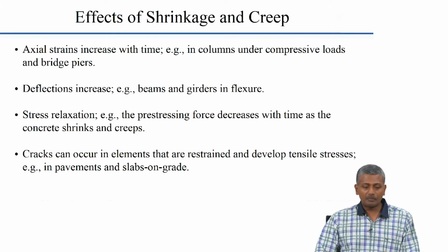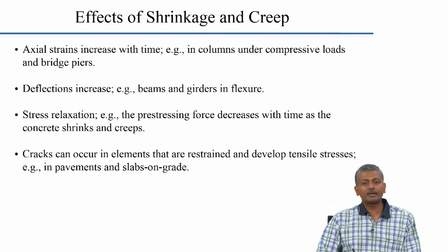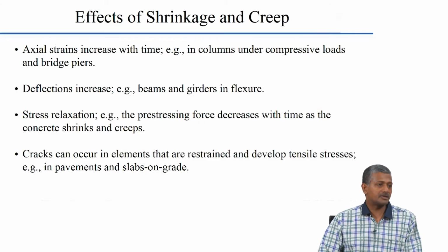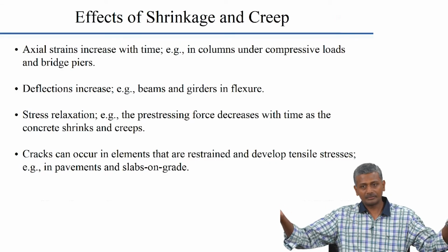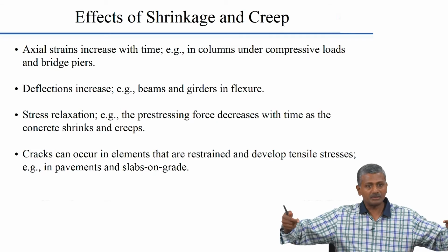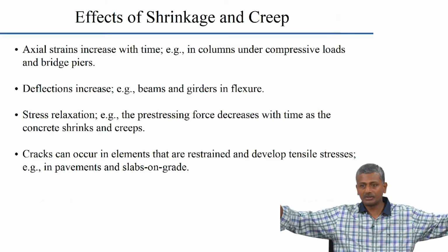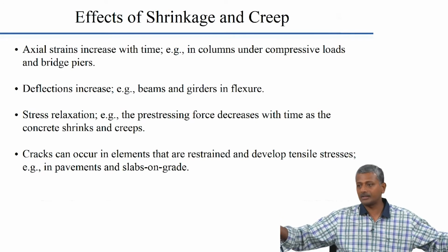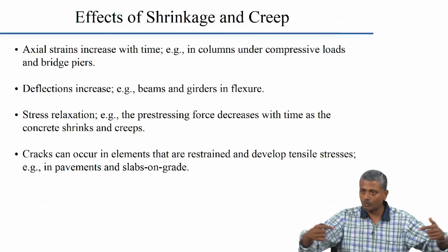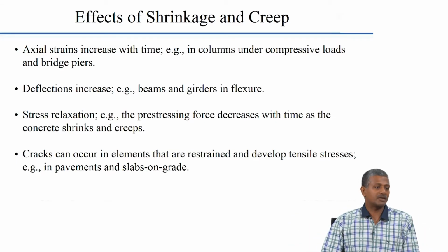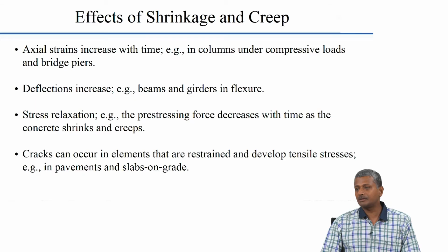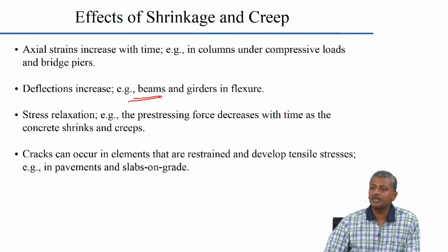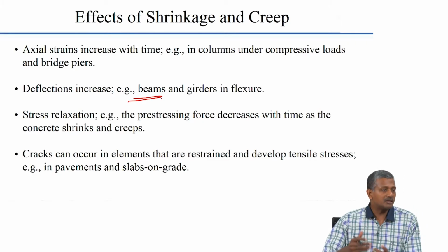So, what happens because of shrinkage and creep? Obviously, if you are looking at a compression member, the axial strains are going to be increasing with time. In the case of a flexural member like a beam, you may have creep and shrinkage happening in the opposite direction. Flexure is going to pull your material. If you look at the bottommost fibres which are in tension, the fibres are getting pulled because of flexure. So, creep will additionally increase the strain in that direction, but because of shrinkage, what is happening? Water is getting lost and your volume is reducing, and so you may have a different opposing direction of shrinkage as opposed to creep. So, there are situations in which creep and shrinkage can result in a collaborative plus effect or a collaborative minus effect. Deflections can increase obviously because of creep in beams. If flexural deflection is happening because of creep, the deflection is going to be much higher.